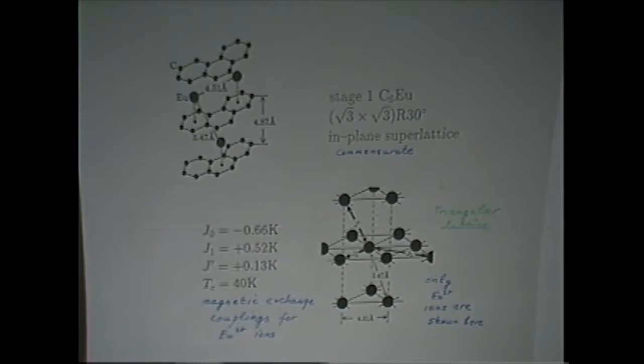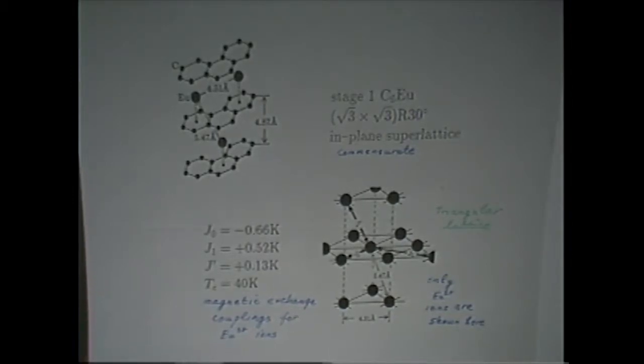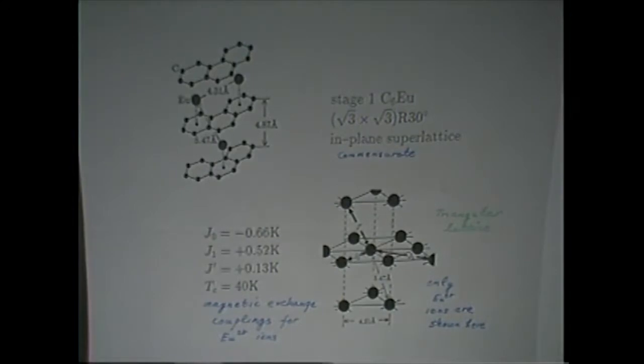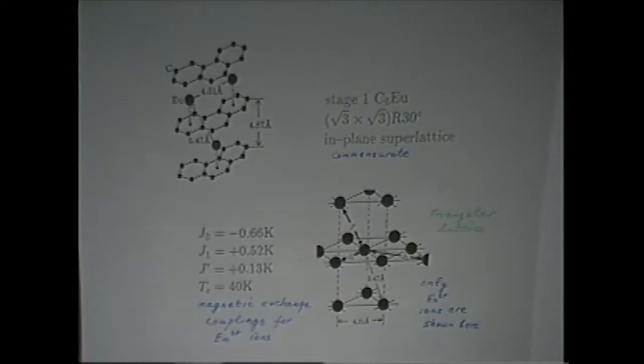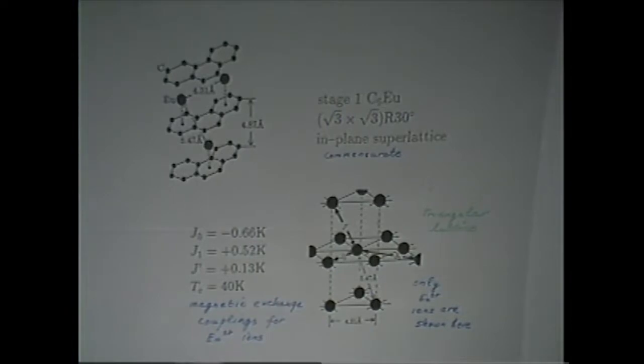The system I'd like to talk about is europium in graphite. Europium is a 4f metal that's magnetic. And the spins in the europium will couple rather strongly to the graphite, where you have a lot of conduction electrons. And depending on the ordering of the spins in the europium layers, you get different kind of scattering in the graphite layers. So we could see magnetic phase changes by monitoring, say, the magnetization, that's one thing, but what I'm going to show you here are results on conductivity measurements. And this turned out to be a very sensitive and kind of a fun experiment. It's kind of nice for this kind of presentation to hopefully some non-experts in the audience as well as experts.